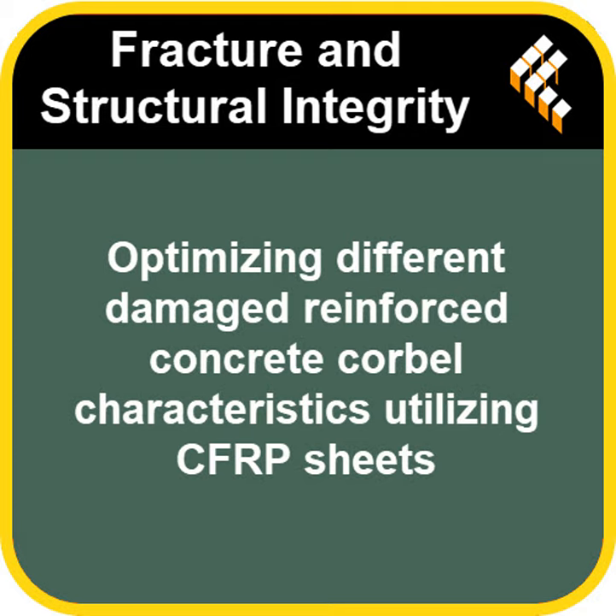But there's a but coming, isn't there? You mentioned the 70% damage level. Yes. This is a really crucial finding. While CFRP helped at 50% and 60% damage, the specimens pre-damaged to 70% showed very little improvement in their ultimate load capacity after strengthening. How little? For the strip-wrapped one at 70% damage, the increase was only 0.51%, basically negligible. Wow. Almost no benefit at that point. Pretty much. It really suggests there's a critical damage threshold.